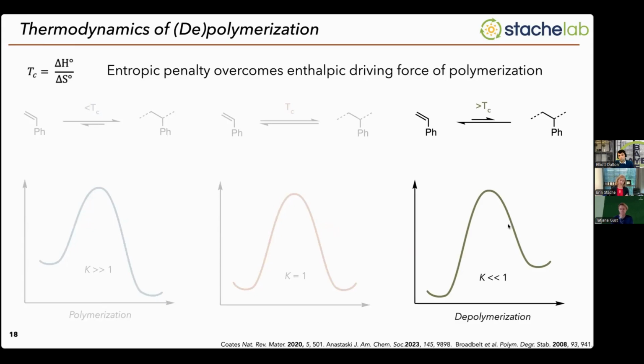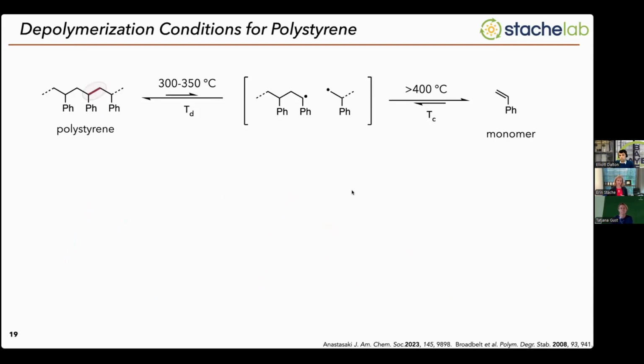We need to be well above the ceiling temperature of the monomer so that we can push the depolymerization back to monomer. Now you can imagine for a lot of our commercial polymers, this temperature is very, very high. And so to reach these temperatures, there's a very high energy input. So for polystyrene in particular, first, if you want to break the carbon-carbon bonds in the backbone, you need to heat this polymer up to about 350 degrees C. That's to just homolyze those carbon-carbon bonds, assuming you don't have any other unique functional group on the polymer, which for most commercial plastics, it will not have. Once you generate these radicals, then the ceiling temperature for styrene monomer is greater than 400 degrees C. And so you really need to be above these temperatures in order to induce the depolymerization back to the styrene monomer. So very temperature intensive.